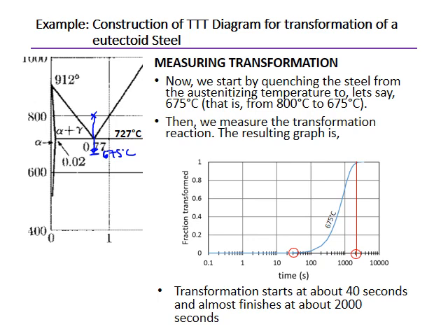But the idea is that you have to find a media, liquid normally, and for that media, it has to be at the right temperature. You have to be able to control the liquid to remain at that temperature every time, and for as long as you are doing the experiment. And you just drop your material from the high temperature to this low temperature. So it's quite interesting, the experimental arrangement for doing this, or the industrial way of doing it. You can do this also in an industry.